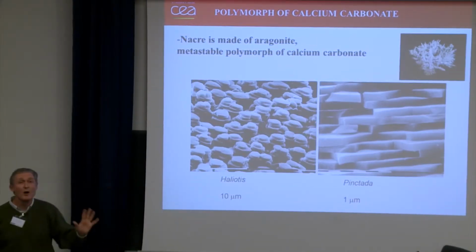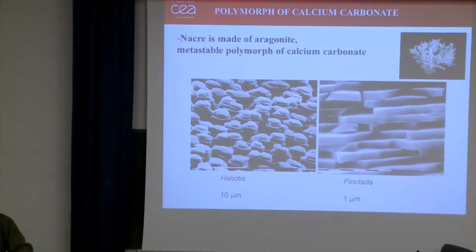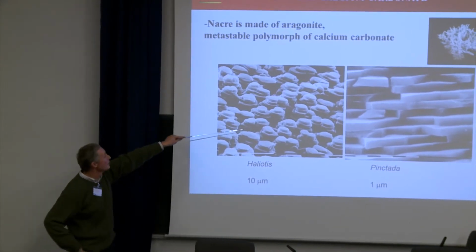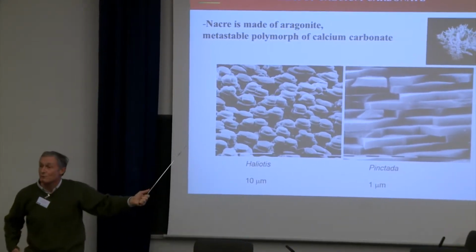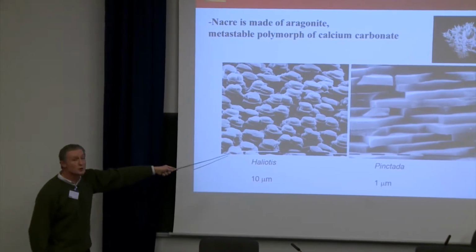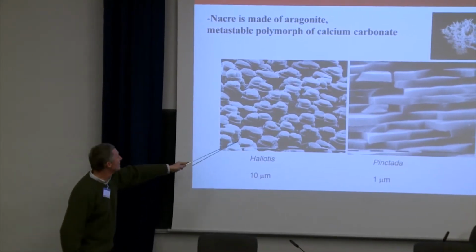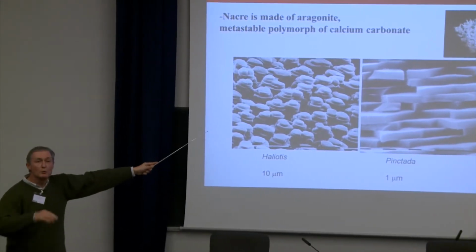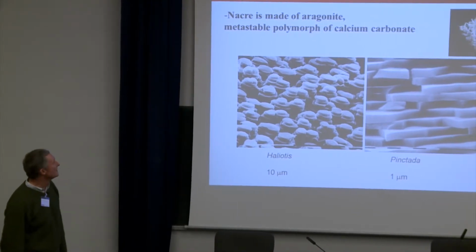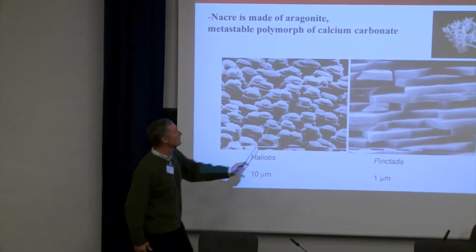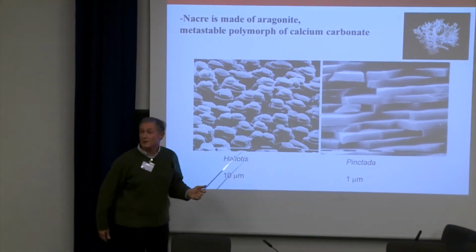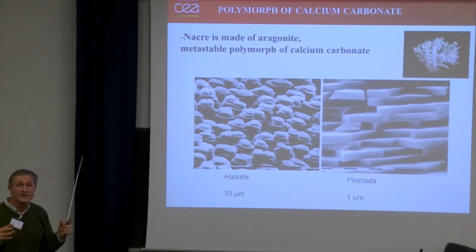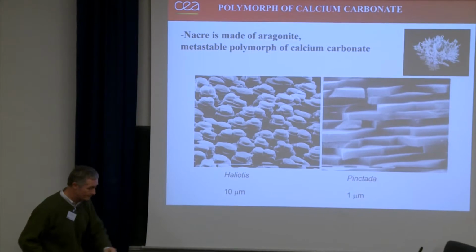Of course, it's only one nacre, and if you look at other animals, it could be very different. This was true for this bivalve, but if you go to different animals like gastropods, like the nautilus you showed before, you would see such an organization. It's always aragonite, but now it builds up as columns and not as a brick and wall structure like in Pinctada. But all of them are very different from the kind of aragonite you could grow in the lab in synthetic conditions. So the shape of the crystal is really dictated by the organics inside.